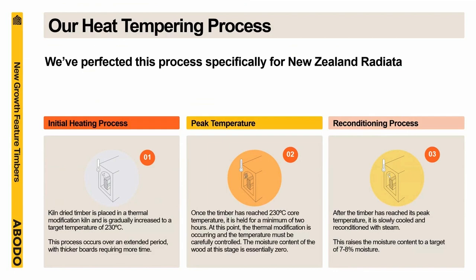It's a three-step process. The first step involves heating the wood gradually up to 230 degrees Celsius. The second step involves holding the wood at 230 degrees Celsius core temperature. It is this point where the modification of the wood happens. From our research, we have found that 230 degrees Celsius is a critical temperature in order to reach the required durability for exterior use in this particular species.